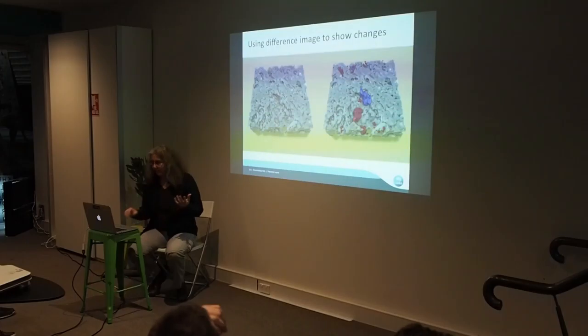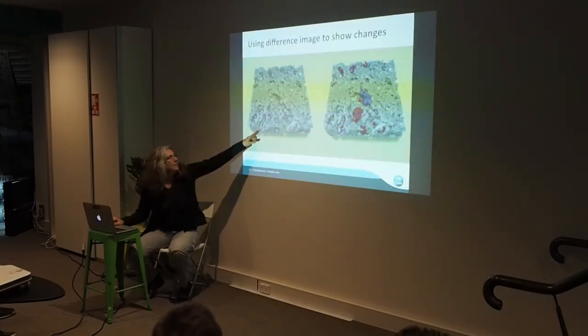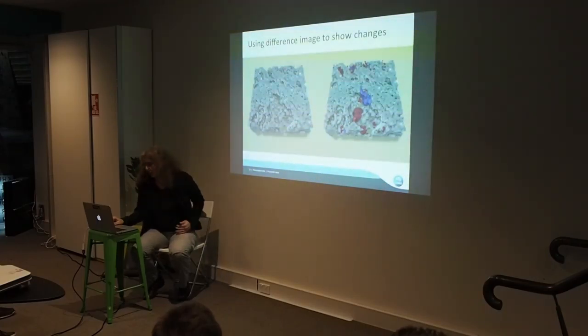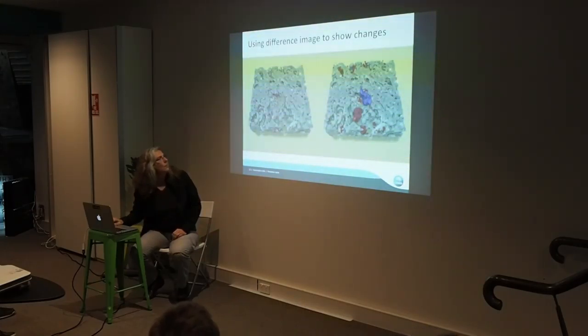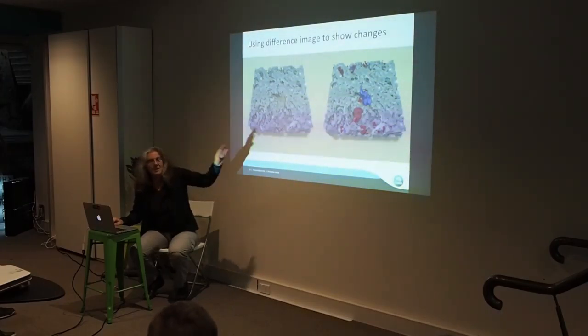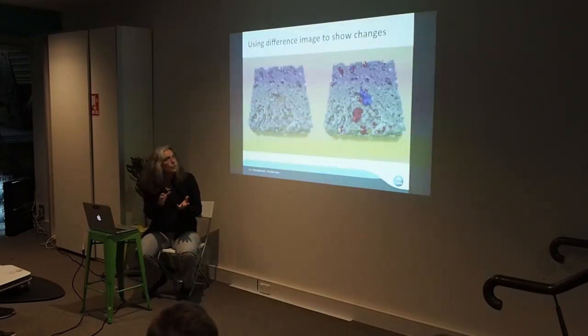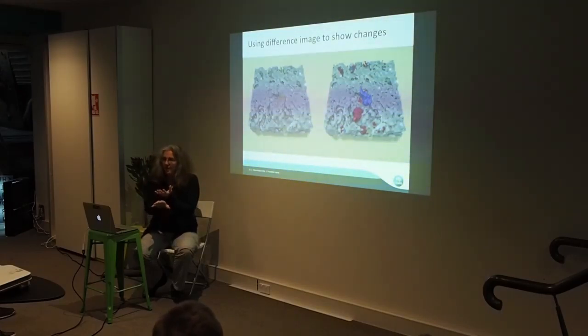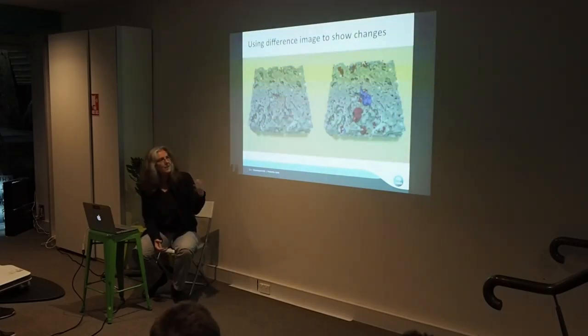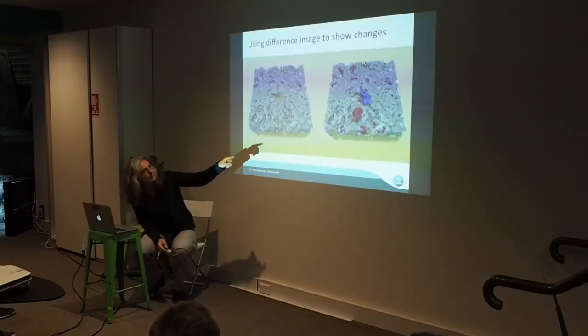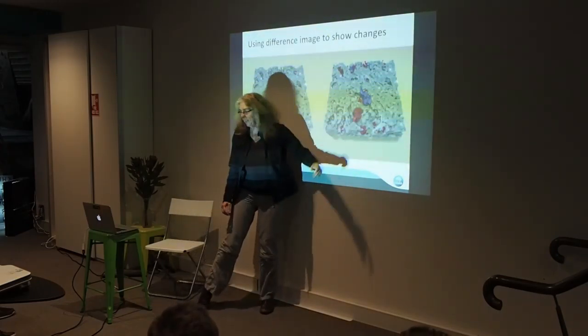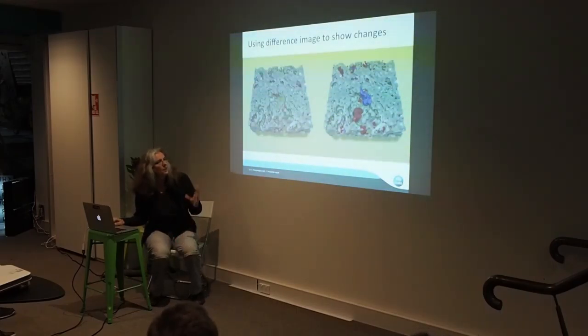We can also do more meaningful things. Here I've used a difference image to show changes. We'd actually crushed these coke samples and we're looking at what happened when we did so. You can see when I go backwards and forwards that some bits break off and move around inside — that's before and that's after. By combining a difference image — this was done in a package called Avizo, which has some useful tools — we were able to align in three dimensions our two data sets, the before and after. Most of the sample is still the same. But by subtracting one from the other, we get positives where something ended up where it wasn't before and negatives where something's gone missing. The blue is where things have gone missing — you can see this lump broke off and ended up sitting there.